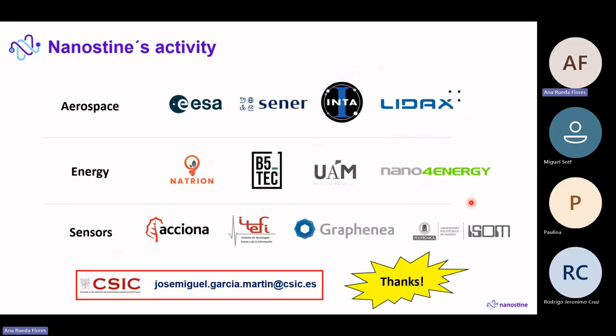Well, the materials, for instance, can sustain sonication without problem. They can also sustain autoclave, that is widely used for biomedicine. But we have just started to measure the mechanical properties. We know that the mechanical properties of the nanocolumns are not as good as those of a bulk thin film, of course. The Young modulus is about 1 order of magnitude smaller. This is what I can say up to now.